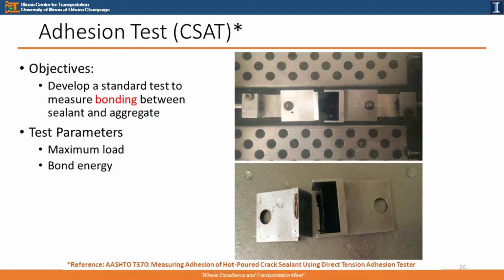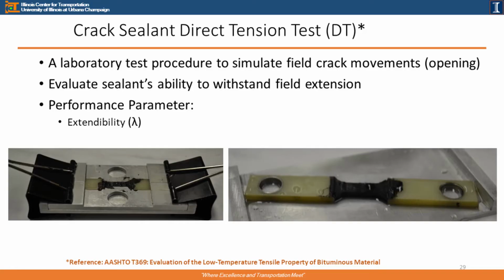This is a new adhesion test. Again, CS stands for crack sealant. The CS adhesion tester means crack sealant adhesion test. And then there is an objective: develop a standard test to measure bonding between sealant and aggregate. And then the test parameter will be maximum load or bond energy. And there is a crack sealant direct tension tester, CSDT.